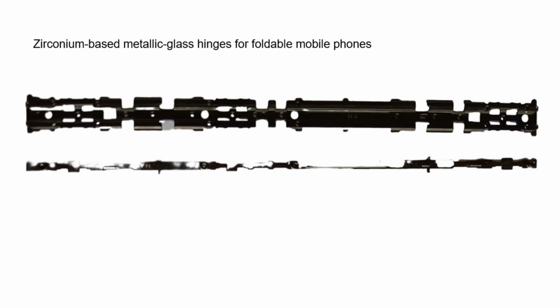The reason is simple. You form the glass from the liquid. There is no crystallization step. So you don't have the shrinkage associated with crystallization, which leads to uncontrollability of shape. When this slide was put together in the summer, approximately 80 million of these had been made by a single Chinese company. It's presumably an altogether higher number right now.